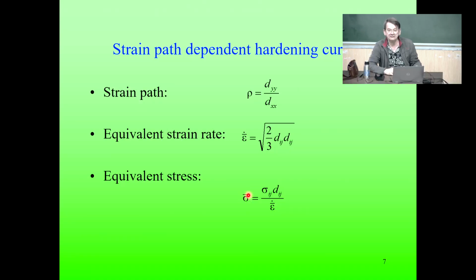work conjugate equivalent stress, which is obtained by, here you imagine that epsilon dot is on the left side. So epsilon dot times sigma is a plastic work. On the other side, component by component, you calculate the plastic work. The two have to be equal. And once you define the epsilon dot equivalent, and we accepted the von Mises one, then this formula gives you the value of the work equivalent stress.